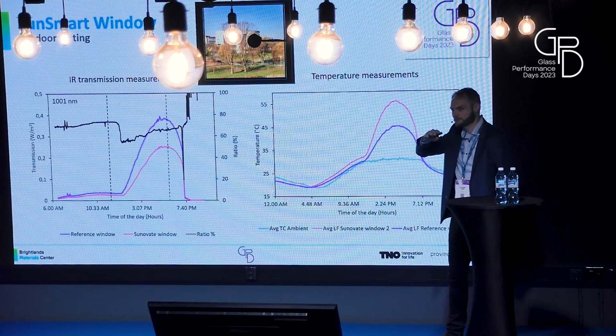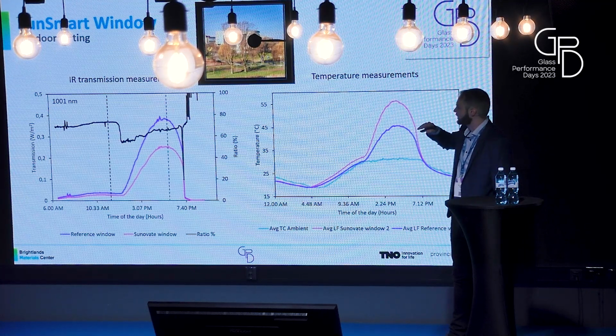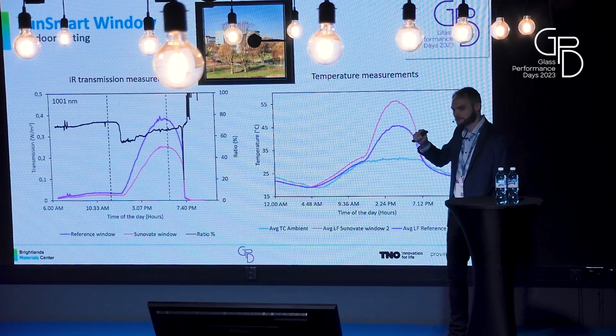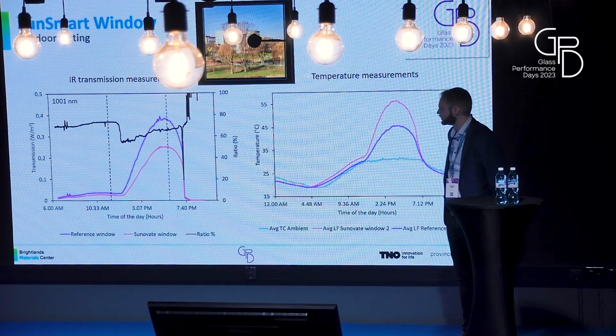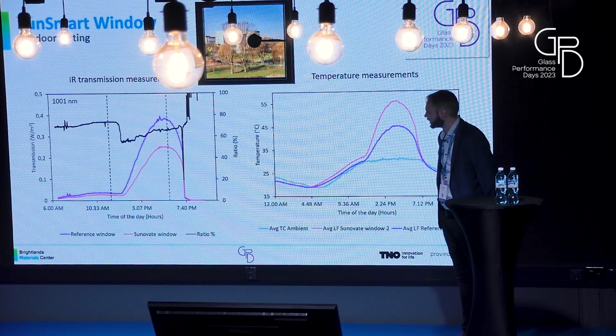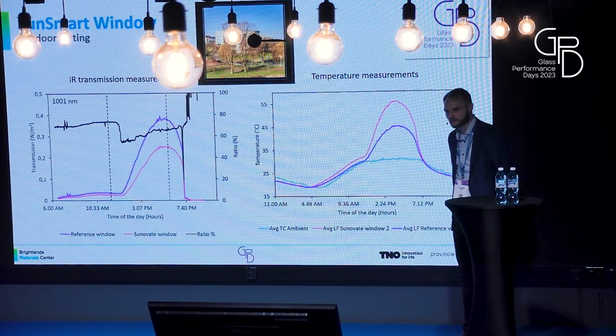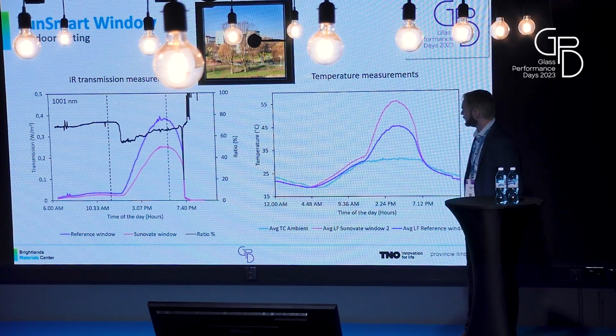So we first have a steady ratio, which is the cold state. And then when the sunlight hits the window and the window temperature heats up, you see that we have a drop in ratio, which corresponds to a blocking behavior of the smart window.